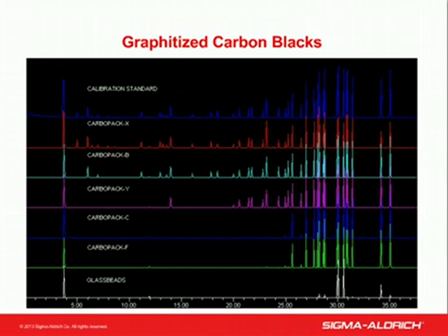And the Carbopack X did a great job of trapping the very volatile compounds, but the recovery of the last two compounds is poor, showing that Carbopack X is too strong for these two compounds. They were irreversibly adsorbed. And then the bottom in white is glass beads, and you can see it only trapped the high molecular weight compounds, and in fact these even had breakthrough.